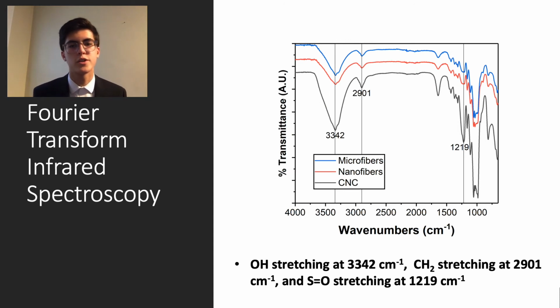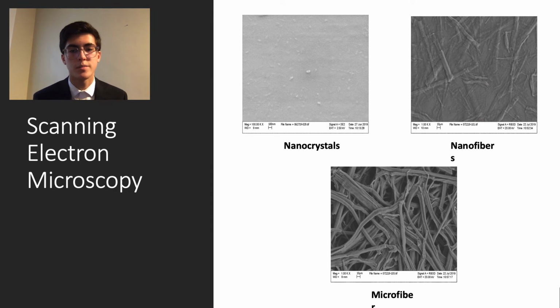Fourier transformed infrared spectroscopy, or FTIR, of nanocrystals, nanofibers, and microfibers all show OH stretching at 3,342, CH2 stretching at 2,901, and S double bond O stretching at 1,219. Essentially, what the OH stretching and CH2 stretching confirm is that all materials have a cellulose backbone. What the S double bond O stretching would seem to confirm is that sulfonation was successful for all three materials. Scanning electron microscopy images confirm that nanocrystals and nanofibers exist in nanoscale and that the microfibers are partially defibrillated and have a larger bulk morphology.